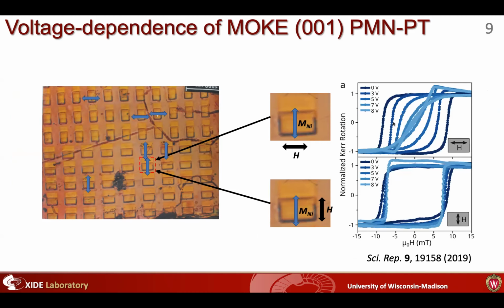But what we found is when we can measure multiple electrodes in different orientations, every single one of them would consistently rotate that anisotropy towards the short axis of the electrode. So this started to give us an idea that the geometry of the electrode was an influencing factor.